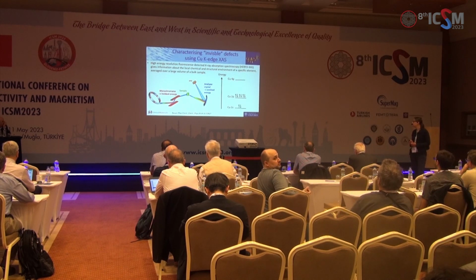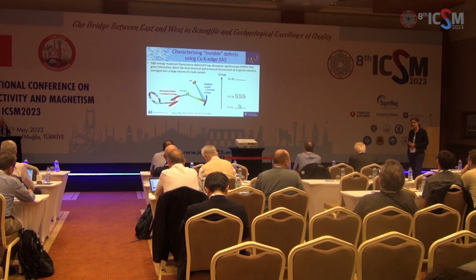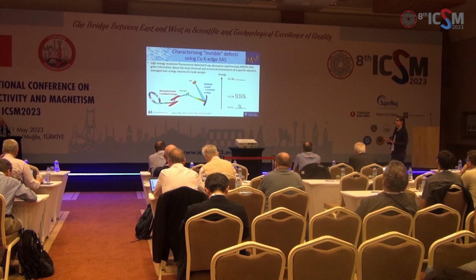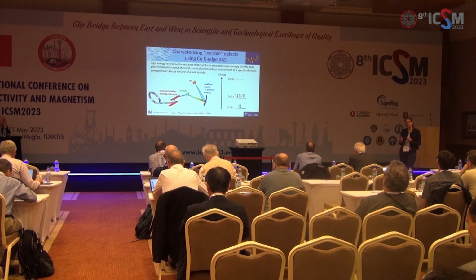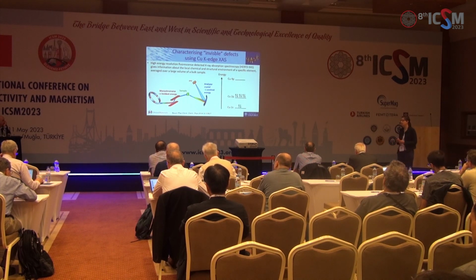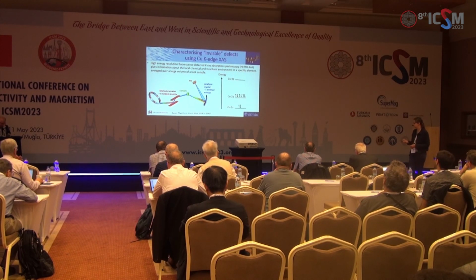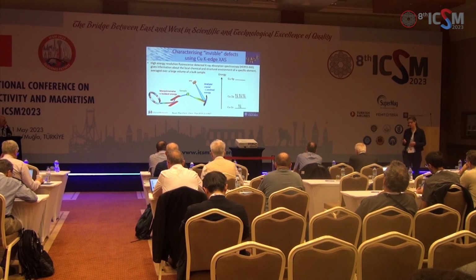And the method that I've been using is high energy resolution X-ray absorption spectroscopy. So absorption spectroscopy is sensitive to local chemical and structural changes around a particular chosen ion, or atom, in your structure. And here we've been looking at the copper environment. So we've been using hard X-rays to probe the chemical environment around the copper atoms. And we do it with an experiment at Diamond Light Source that looks like this. We scan the incident beam energy across the absorption edge, and we detect what's going on using fluorescence.